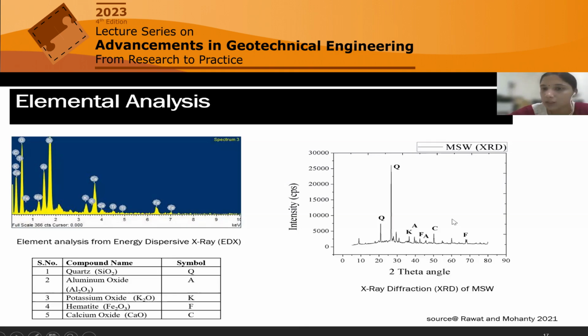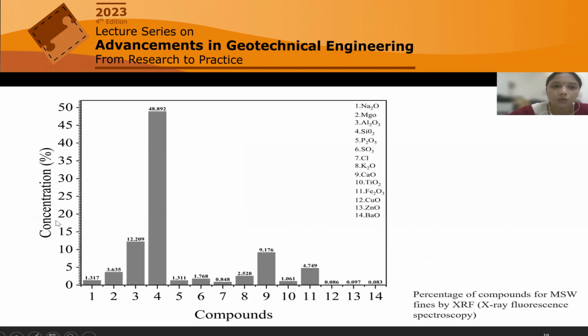On the right side is the XRD graph, and here you can see compounds like the minerals quartz, aluminum oxide, potassium oxide, and hematite are present. And this one shows the concentration of compounds present in MSW fines. If you see, nearly 49% is this fourth one, silica content, followed by alumina. Alumina is this one, 12.2, and then this ninth one is calcium oxide. This has been obtained from XRF results, and this test was conducted in the CSIR lab in Bhubaneswar, because we don't have this facility here. IIT-BHU has an XRF facility.